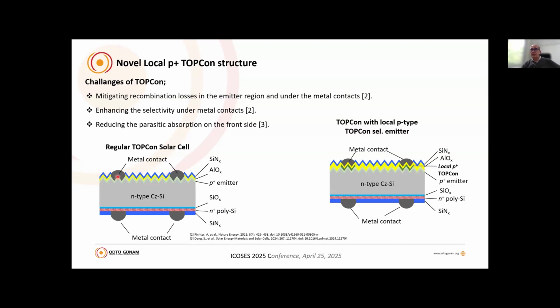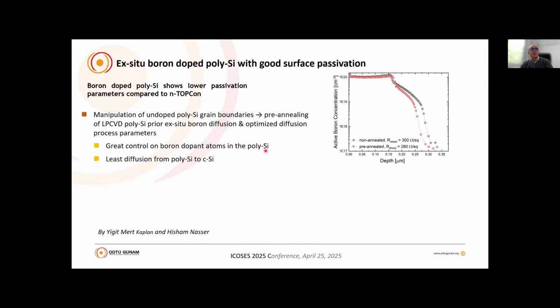Here you can see more details on the right side. We have a local P plus TOPCon structure under the metal, but the rest of the emitter region is not covered with any poly layer, of course. This is the so-called local TOPCon structure. Here, of course, you have a very important patterning problem. You need to pattern the poly layer on the front side. So this is something that we have studied.